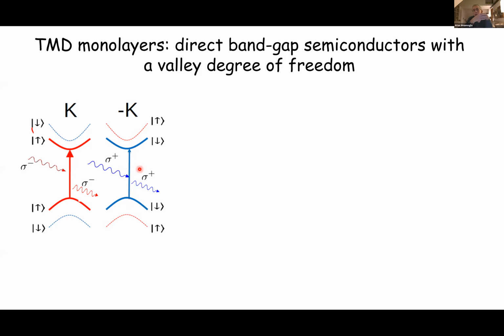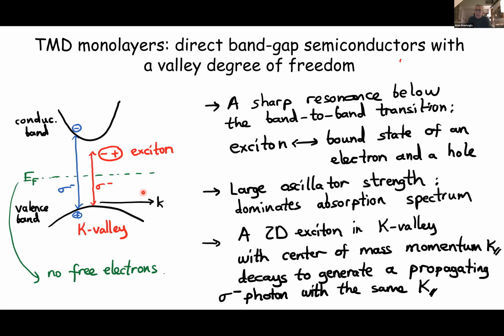Very small, on the order of 20 times smaller than the binding energy, but in this case, still on the order of 15 milli-electron volts or so. So the inter-valley excitons do not have that, and therefore have even lower energy. And in some compounds like tungsten diselenide, they play a prominent role in determining emission through phonon-assisted processes.